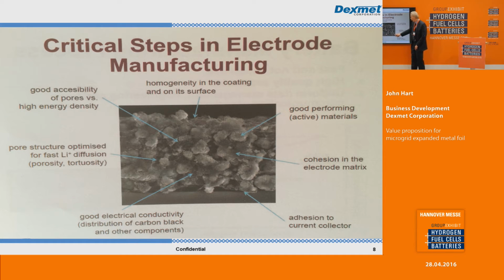The other type of binder is used to adhere to the solid surface down here. But if you look under this SEM photo, in a very close-up, you've got less than 50% of the electrode material actually making contact with that foil. So it requires a pretty aggressive binder to adhere to this and maintain the cycle life without breaking that apart. So anything you can do to reduce the amount of binder in here, which is a cost to the battery, and eliminate the weight that binder causes, is a good thing.